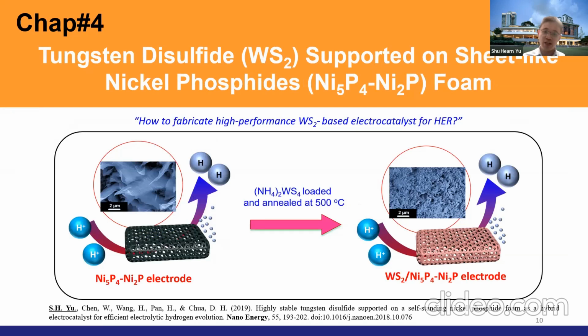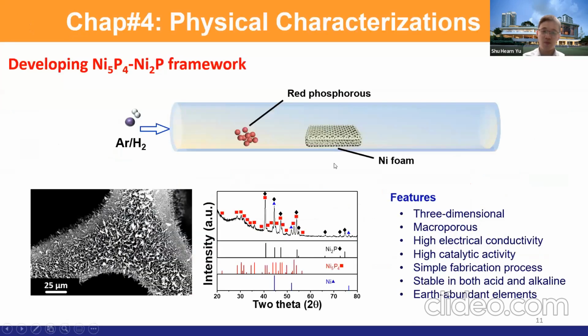So in this project, I try to fabricate a nickel phosphide electrode, and after that, I soak this electrode into the catalyst precursor, and then anneal it at 500 degrees C. And then I get my hybridized electrocatalyst. Then this hybrid electrocatalyst performs better than WS2 and also the nickel phosphide electrode itself, the standalone electrode. So this is the experiment setup.